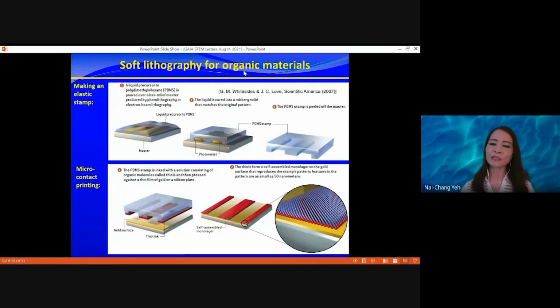But what about organic materials? With organic materials, you cannot do it the way I just described. One way is called soft lithography. First you use the hard lithography that I just described to create some structures. Then you put some polymer on top of it, and when the polymer is cured and hardened, you can peel it off. So you create a structure with hard techniques, and now you have a polymer that replicates the structure you just created as a negative. Then you can press this polymer onto some kind of organic ink.